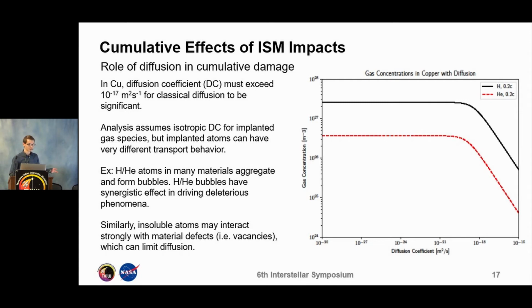For example, hydrogen and helium atoms in many materials aggregate and form bubbles, and the hydrogen and helium bubbles together have synergistic effects that can drive deleterious phenomena further. Similarly, insoluble gas atoms may interact strongly with material defects, as I described before. So therefore, an understanding of hydrogen-helium interactions in a solid, interactions with material defects, defect production by irradiation, and interaction of near-surface gas atoms with material surfaces will be necessary to design materials resistant to bubble formation, cracking, and blistering.